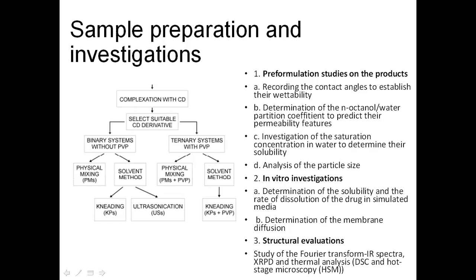During the solvent method, we applied kneading and ultrasonication, and of course, after the evaporation of the solvent, which was ethanol, we got the dry products. During the ternary system formulations, we prepared first the physical mixtures, after which we used the kneading procedures.